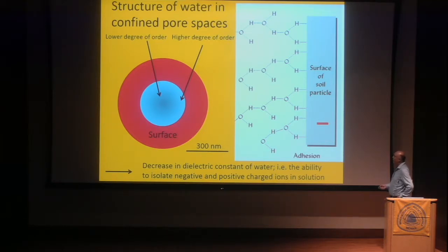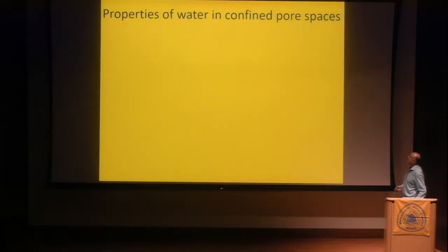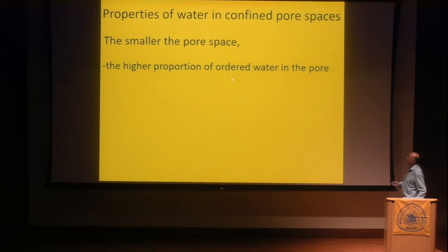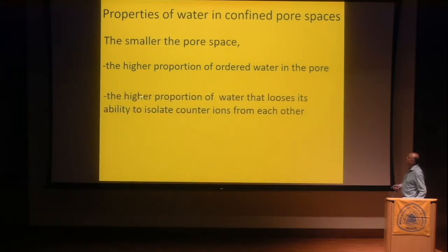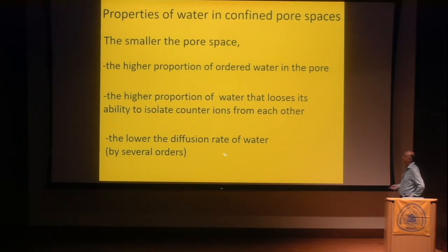So with this ordering degree, we get somehow a decrease in the dielectric constant of water, which means we have a decreasing ability of the water to isolate negative and positive charged ions in solution. So here's a slide summarizing what we so far know about the properties of water in confined pore spaces. The smaller the pore space, the higher proportion of ordered water in the pore, the higher proportion of water that loses ability to isolate counter ions from each other. And obviously, because we are in a confinement, we have a lower diffusion rate by several orders.